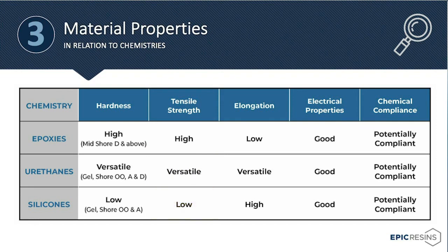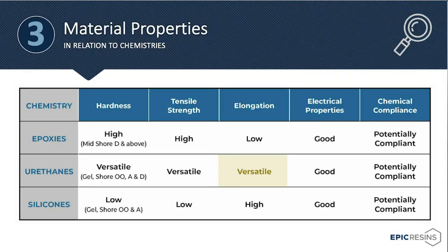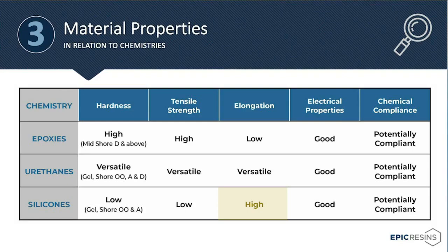Elongation is going to be opposite of tensile strength. So as you have high tensile strength polymers, you're going to have lower elongation. Epoxies, for example, have low elongation because they're more rigid and have higher cross-link density. Urethanes have versatility because they have versatility in hardness and cross-link density, where we can have both low elongation and high elongation urethane polymers. Silicones are going to have high elongation. They don't have the ability to have low elongation, and that primarily comes from the nature of the backbone of